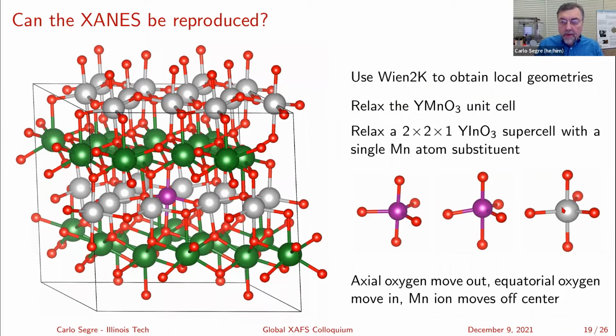On the other side, we have the yttrium indium O3, and I tried to make these to scale so that you can see that the arrangement around the indium is also relatively symmetric, but it's bigger. That is, the distance from this oxygen to this oxygen is significantly larger than the distance from this oxygen to this oxygen.